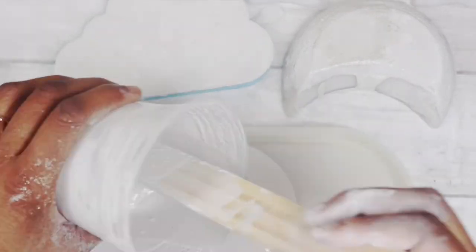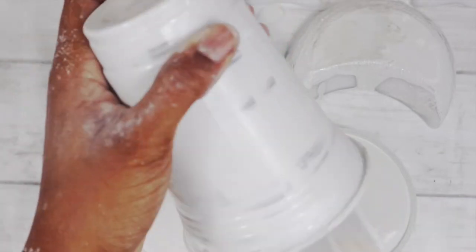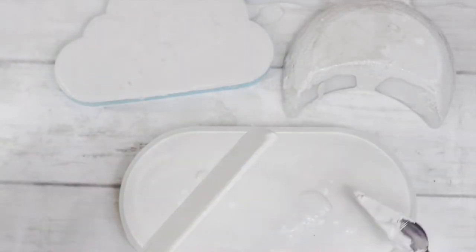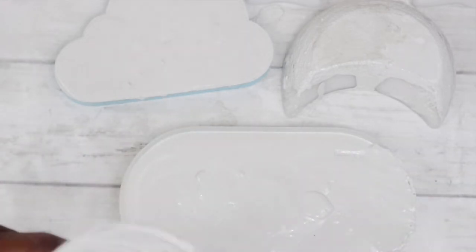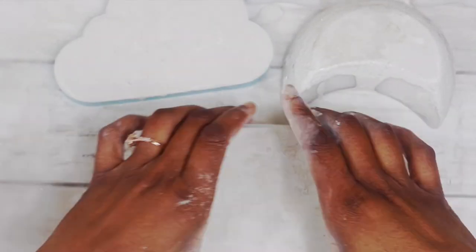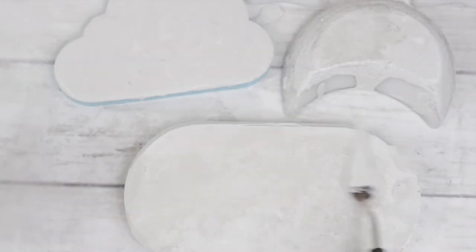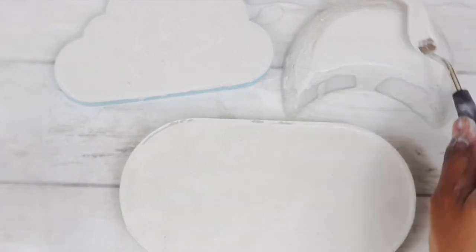This is the color I've been trying to achieve, and I've finally achieved it with titanium dioxide. Here's my chicken tray mold — I was trying to remake that cowhide look. Do remember that the acrylic polymer has a slower drying time than water, so it's not a four-hour cure. It's more like eight hours — you can even leave it and de-mold the next day. That increased work time means you're not rushing the mixture into the mold, which helps a lot.